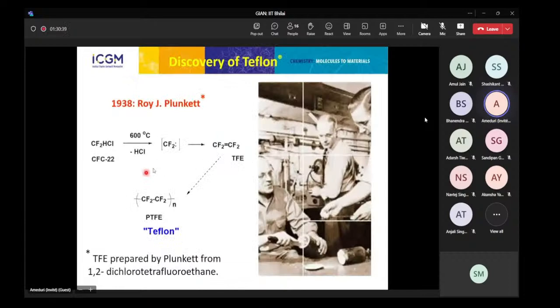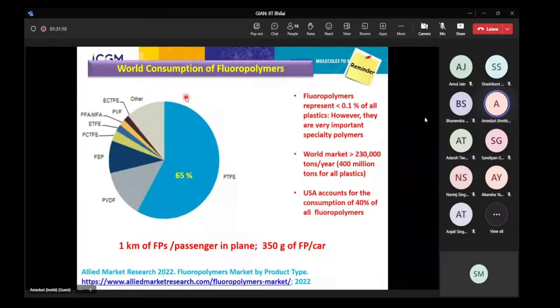So I come back to this slide, which is interesting because Teflon was accidentally produced by the use of difluorocarbene, which was generated by the pyrolysis of CFC22 in order to make TFE. This difluorocarbene recombined in order to make some TFE, called Teflon because it was in DuPont. And they observed a white powder which was insoluble in all solvents and very high thermal stability. So PTFE has the highest production volume, followed by PVDF, FEP, and some estimation trends show that more and more PVDF will be produced because of the binders for lithium-ion batteries.